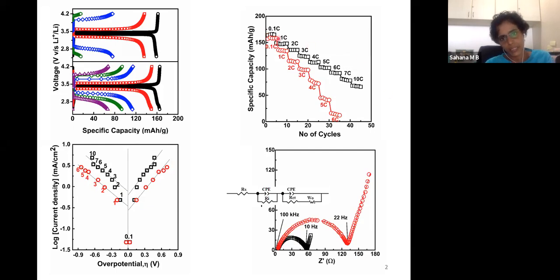Which can be seen also in the right top graph, which shows the black small circles. It shows the premixed energy or the specific capacity at the different charging rates and discharging rates. Here where we premix, the mixing is very good. Mixing is good means in an electrode, the carbon black and LiFePO4 are uniformly distributed. Carbon black covers LiFePO4 uniformly, far better than in this first case, where the charging or discharging doesn't happen at high C rates.